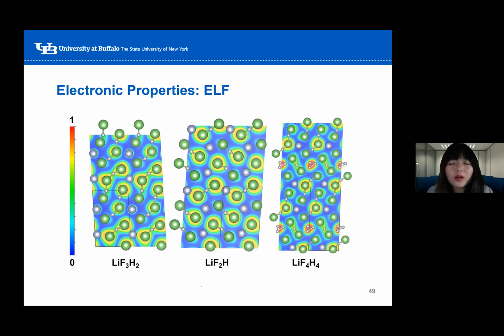So we plot the electron localization function as a contour for the 3 selected structures. There are missing points in the contour because it's really hard to choose a perfect plane that covers everything. But we can still see that there are very high ELF regions around the H3 cations because it's a 3-center 2-electron bond, and there are high ELF regions located around the F atoms, and the ELF around the shorter and stronger FH bond is higher than that of the longer bonds.